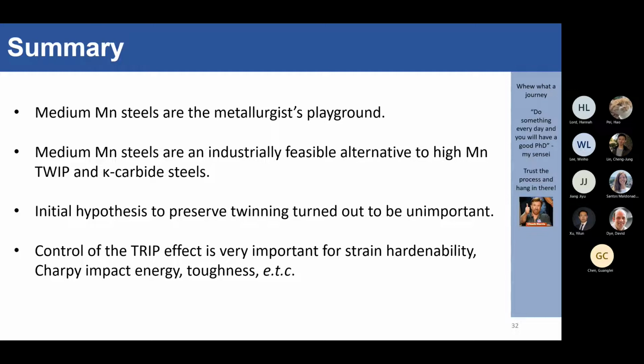We've shown that medium manganese steels are an industrially feasible alternative to your high manganese TWIP steels, because we can actually homogenize it within a sensible time in a reheating furnace. And unfortunately, medium manganese steels also show that the initial hypothesis of making a manganese-lean TWIP steel was totally irrelevant. And that was because it was the TRIP effect that was really dominating your stress strain behavior. And therefore, control of the TRIP effect is now very important for factors like strain hardening, Charpy impact energy, and so on.